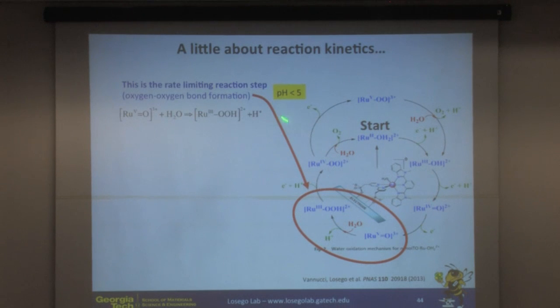Okay, so at pH less than 5, the mechanism for this reaction is just direct attack of a water molecule to the ruthenium 5 complex. As we increase the pH, we now have some sort of conjugate base species that can abstract a hydrogen from a water molecule, creating an atom proton transfer process that facilitates the attachment of this OH group to the ruthenium 5. That's of course an easier process to facilitate, and so it has faster reaction kinetics.